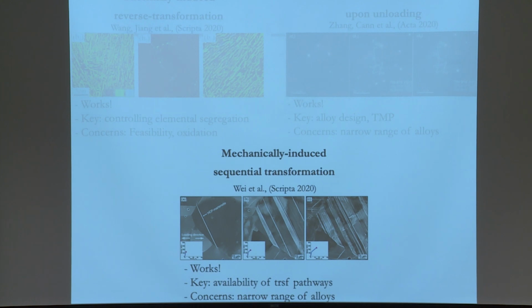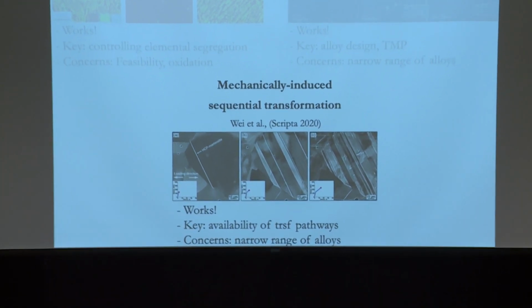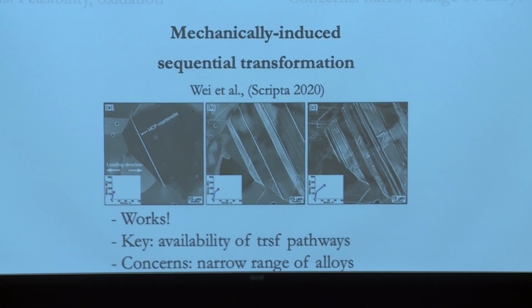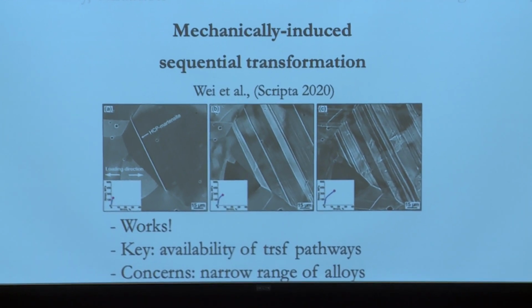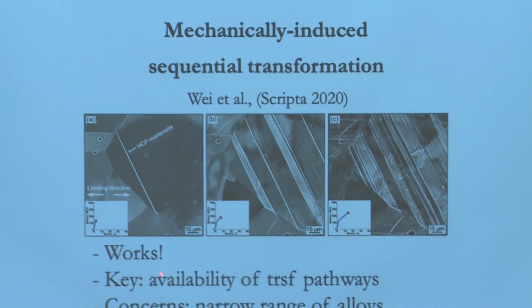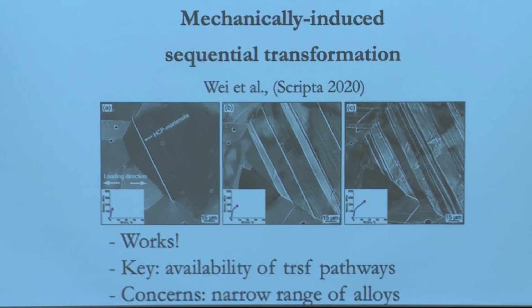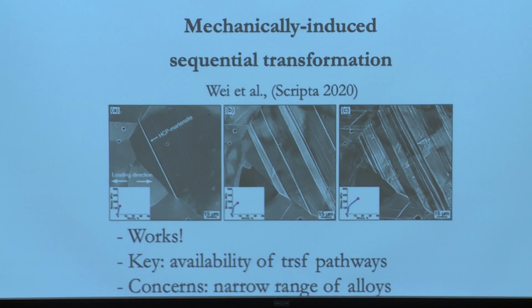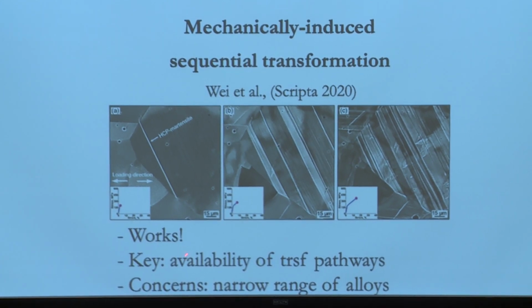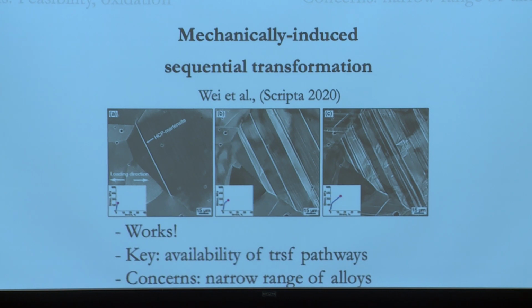All right, so if we take a step back again, what was the idea here for this third solution? That is that you would design a microstructure that would now show two transformations. And these kinds of transformations would perhaps delay damage nucleation to higher strain. So you make a better material, essentially. So it seems like this idea also works. The key here is the availability of transformation pathways. So you can't go from every crystal structure to another, so you need to have a transformation pathway to realize it, which also, of course, creates a limitation in the range of alloys that you can design for this purpose.